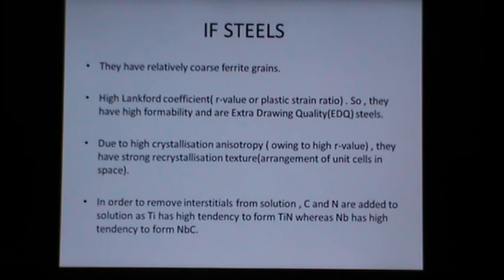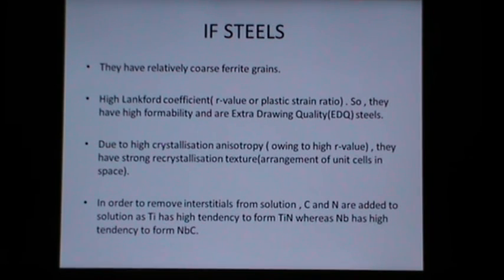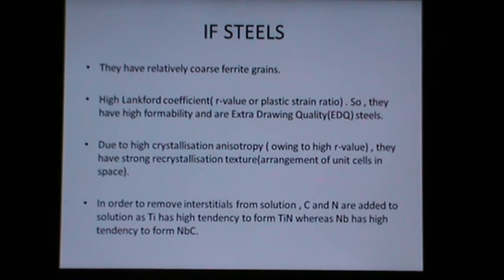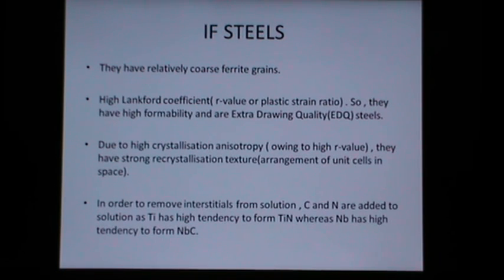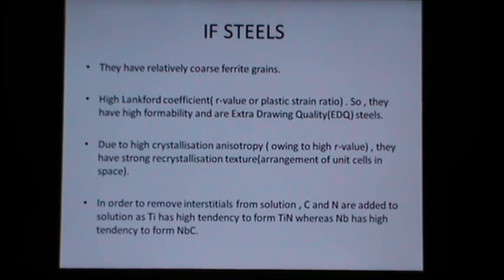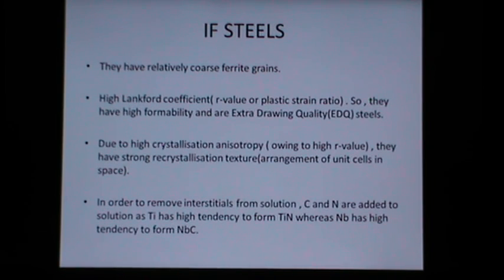Depending upon the formability of different grades of steels, there are three types of drawing quality steels: drawing quality (DQ) steel, deep drawing quality (DDQ) steel, and extra drawing quality (EDQ) steel, which has the highest formability. For IF steels, there is high recrystallization anisotropy leading to a high R-value, giving them a strong recrystallization texture.